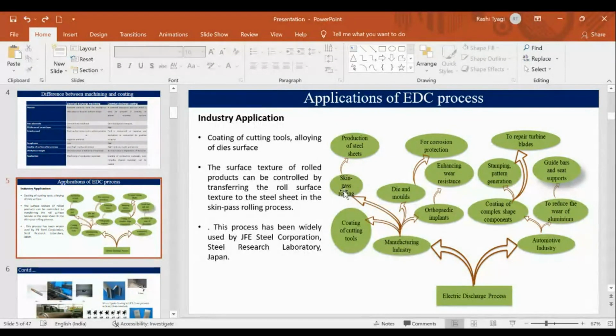Similarly, in skin pass rolling, basically there is the steel industry in which rolls are used to compress the sheets for the production of sheets. So we provide the texture on the roll, such that the texture of the roll can be transferred to the workpiece, to the steel sheet surface, because we want to hold the oil between the roll and the sheet. So we use texturing on the surface of the roll.